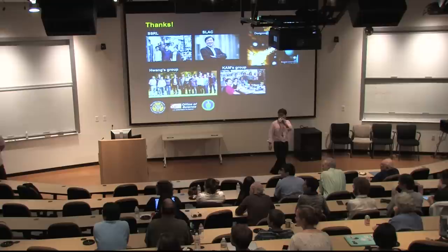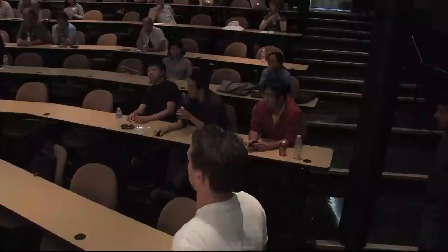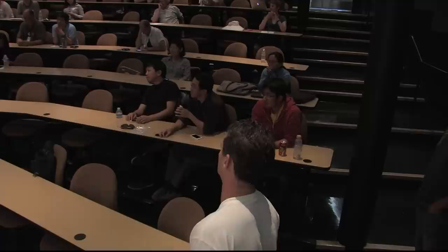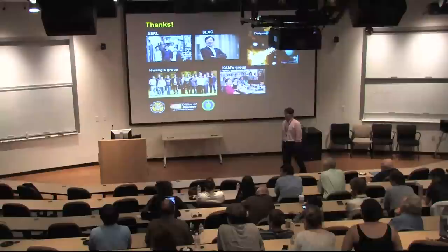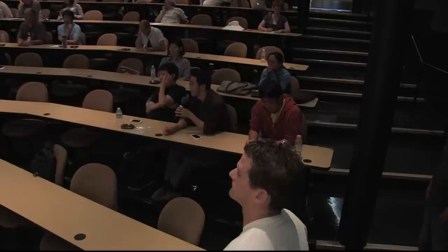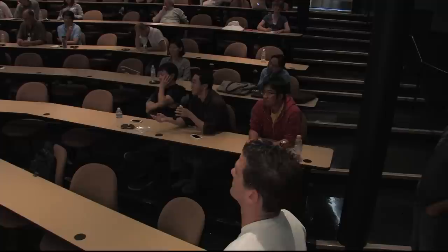Very nice talk. A simple question and maybe a harder one. The simple question is, has anyone really measured the critical field in this interfacial superconductivity? When you say you need 30 Tesla, I'm just wondering, has anybody really measured the upper critical field of this material? No, not yet. So when you say 30 Tesla, that's implied from high-Tc materials, where the upper critical field is measured. Yeah, according to YBCO or some other cuprates. So the minimum we need is 30 Tesla or something. But this is only 200 millikelvin, even higher.